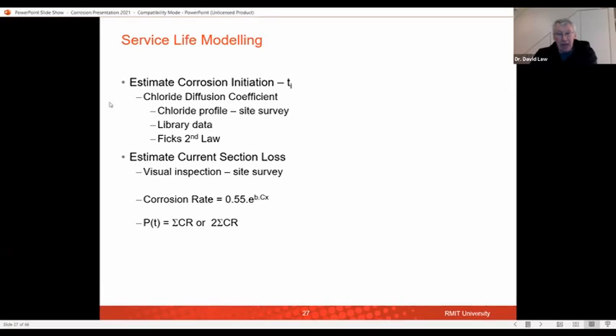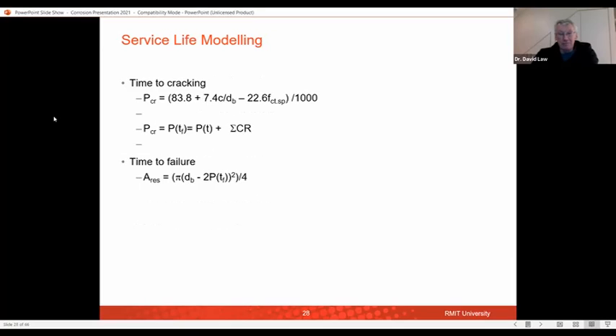So this is how we can go through and estimate our section losses, and our corrosion rate can then be correlated to how much we lose over a longer period of time. So there are various ways that we can then go forward to estimate the service life of our structure based on the information that we've got from our corrosion rates. And thus, in the end, we can get actually to our residual section, which is the main thing we're interested in. And so this is the residual section of our steel that is related to our penetration depth. So we can get what we say is our time to cracking, and we can get, most importantly, that time to failure that we can try and estimate from our corrosion rate measurements.